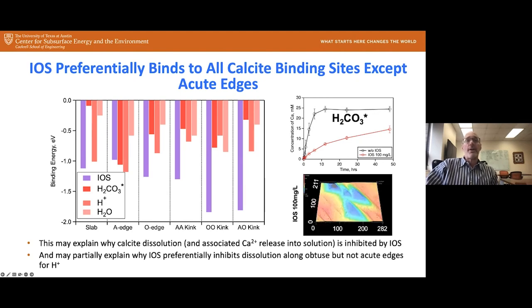All right. The other thing we see is that, remember, for the proton system and the water system, we went from the rhombohedral shape to this truncated shape where we were no longer getting etching along the obtuse direction, but we still got etching along the acute. And here we see the proton has a greater adsorption energy on the acute edge than IOS, so that would indicate we should have propagation or dissolution of this etch pit in the acute direction, but not the obtuse. And so that could explain that observation. So that's a really nice agreement with result, but not across the board. And I'll come back to that.